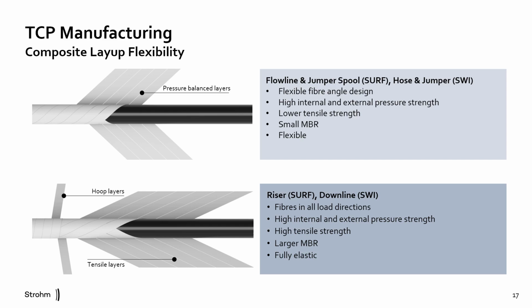For risers, or indeed any pipe that requires high tensile capacity, we do things a little differently. Within the composite structure, we actually vary the tape lay angle significantly. This allows us to maintain the balance between internal and external pressure capacity, while adding more fibers in the axial direction to achieve the tensile capacity. As with any balance, if you offset one aspect, then there's a trade-off. In the case of adding more fibers in the axial direction, we increase the pipe stiffness, and this can lead to a larger minimum bending radius.